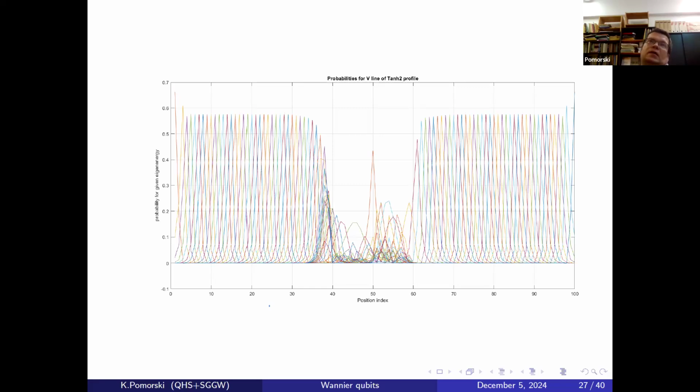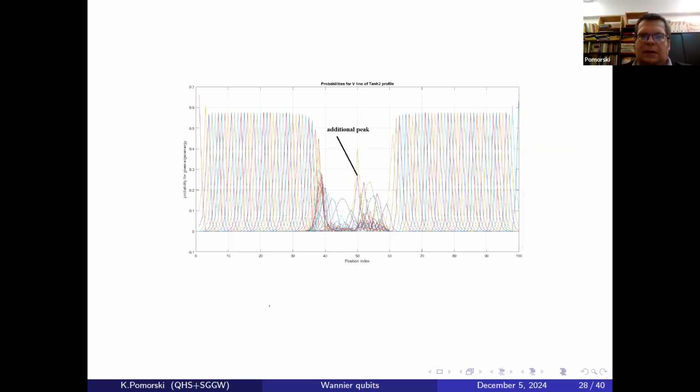The story of bending is not only applicable to semiconductor nanowires. You can apply it to superconducting nanowires. You can also make interesting Josephson junctions. Usually a Josephson junction is superconductor, insulator, superconductor, and this insulator in between is the natural barrier that separates two regions. But it might turn out that you don't need to put an insulator in between. You just take a superconductor on a wire and bend it, and this bending is semi-equivalent to the insulator. So you are dealing with one piece of material that you are just shaping. That's also much nicer from a technological perspective. So that's one of the directions.